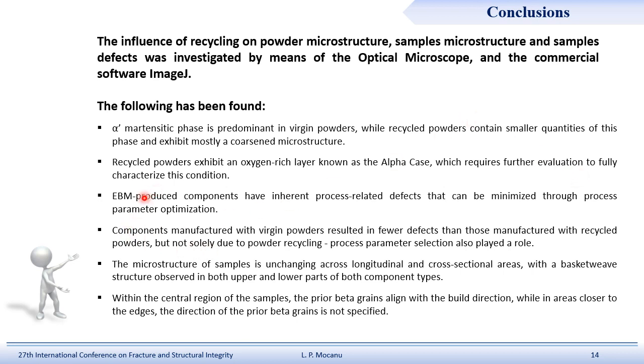Then regarding the components, we saw that both kinds of components are characterized by the typical defects in the electron beam melting process, and they are mainly due to the process parameters, while the only defects which are due to the powder recycling are the tiny porosity, which is due to the gas entrapped in the powders itself.